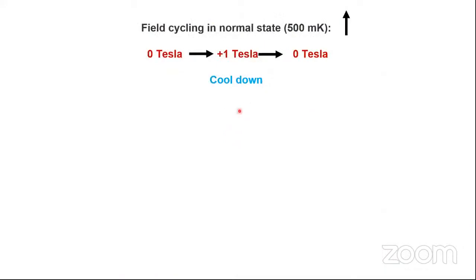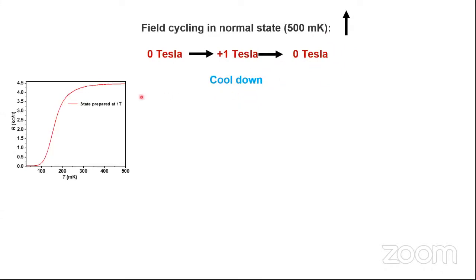Now, as I mentioned, LVO is an interesting ferrimagnet. Now, what is it doing in this case? In order to study that in detail, we exposed the system to controlled magnetic fields. What we did, we warmed up the interface to 500 millikelvin, which is the normal state. The superconducting transition temperature is around 250 millikelvin. And we ramped the magnet from 0 Tesla to +1 Tesla, and then ramped it down to 0 Tesla again. So at zero field, we cooled down the interface, and we found that the superconducting transition temperature